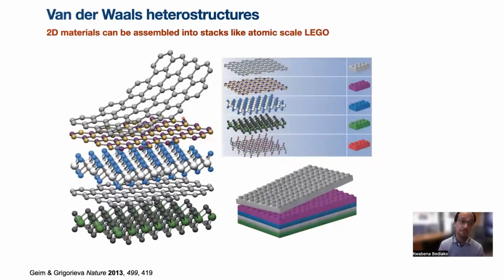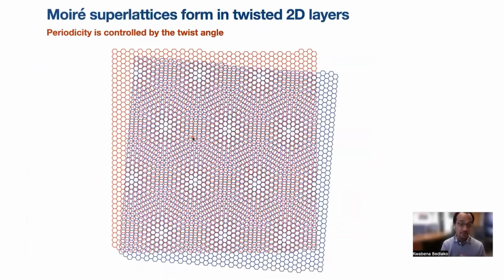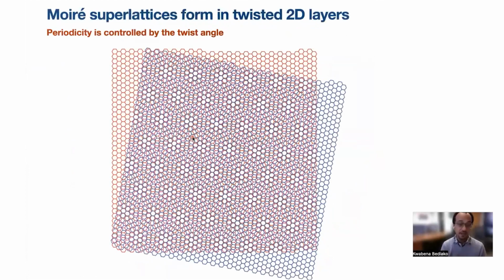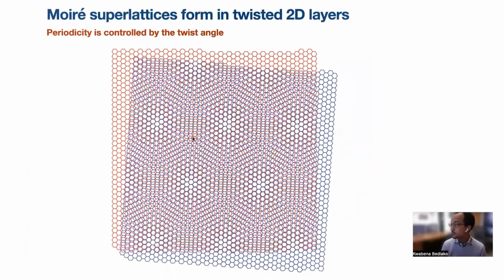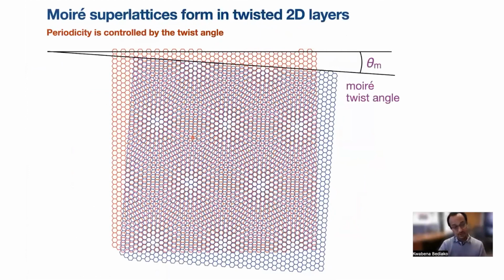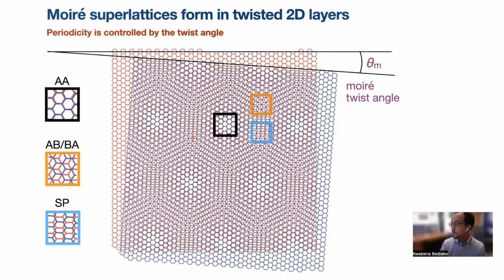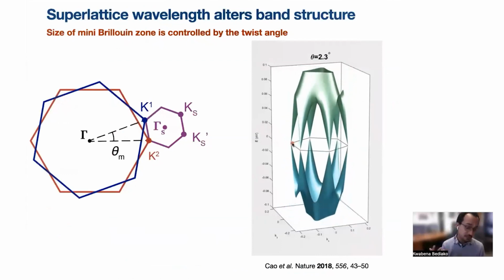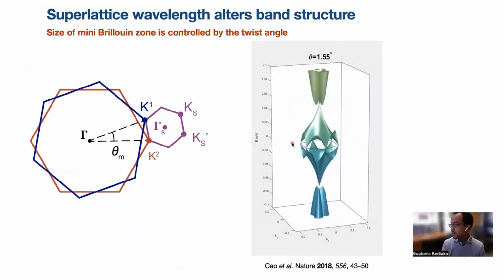And as you heard in the previous talk, these layers can slide over each other and form these Moiré superlattices, where the twist angle controls the length scale of this Moiré superlattice and basically the crystallographic registry between the layers. And so in this Moiré superlattice, you have different types of stacking. What is changing as you go from one region of the Moiré superlattice to another is just how these lattices are on top of each other. And since about 2011, it was known that as you change the twist angle between graphene layers, you expect really flat bands to emerge in the band structure.